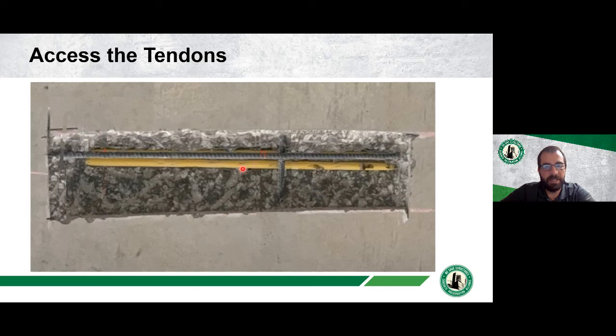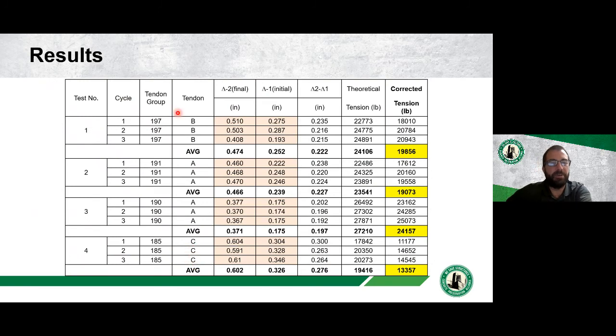And so here, here's some openings. And so here you can see the strand right there. There's another strand right there. And we hook the load frame up and we do a couple of tests and we pull it with a certain load and we measure the deflection. And based on that, we can calculate the tension in the strand.